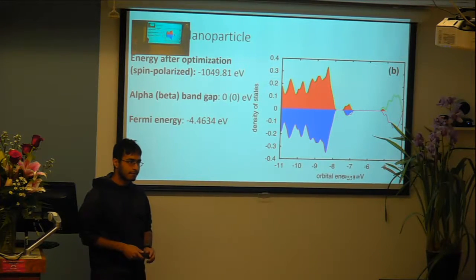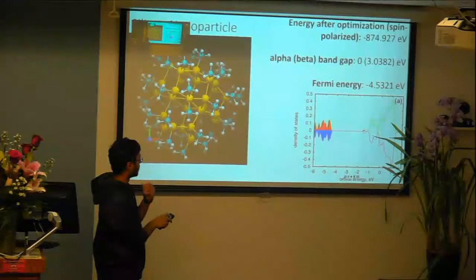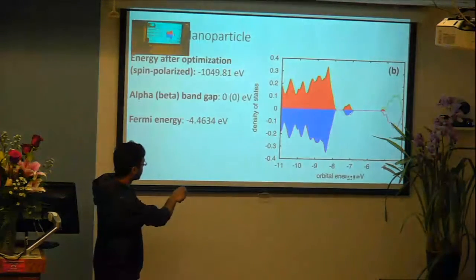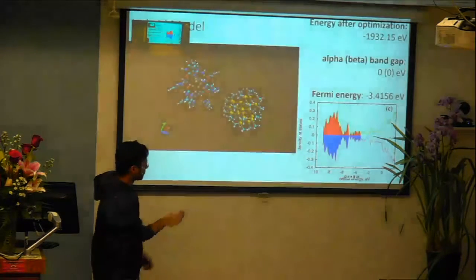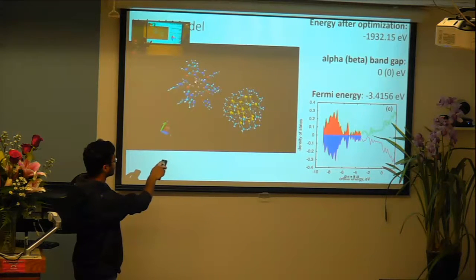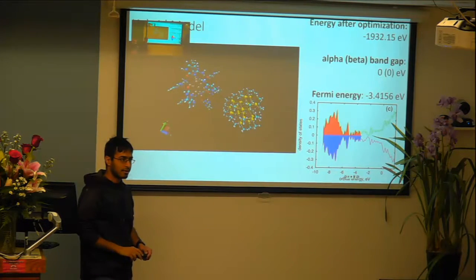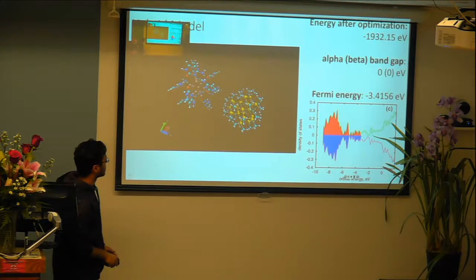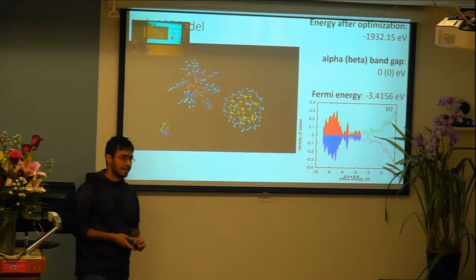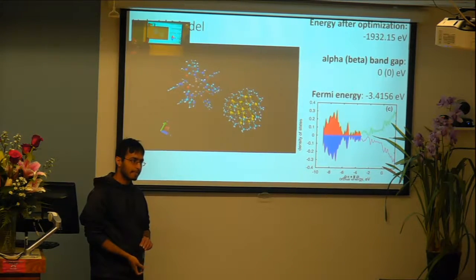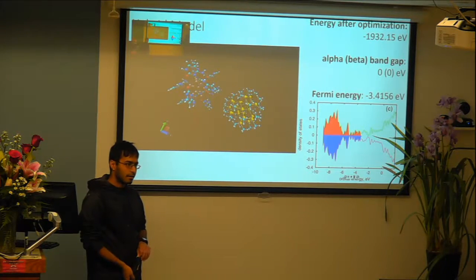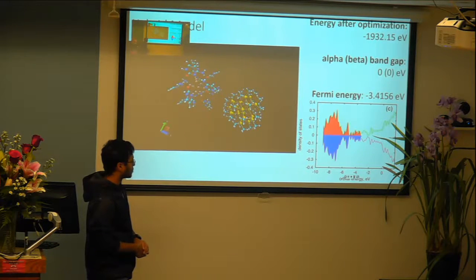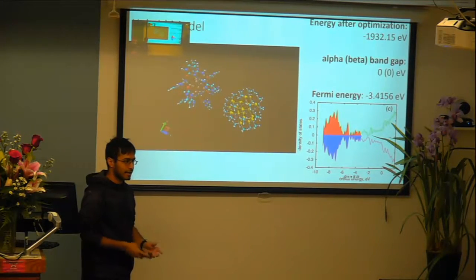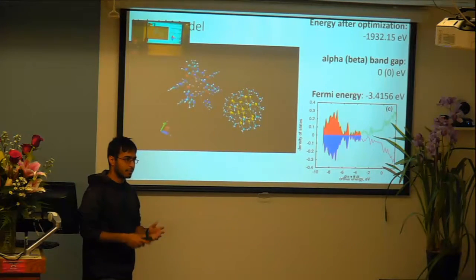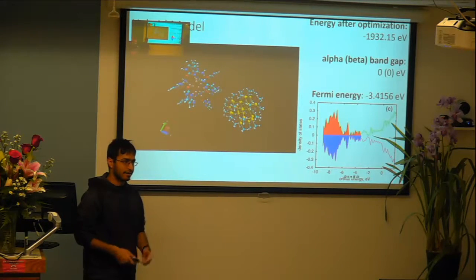And what is the distance between these two, the silver nanoparticle and the silicon part? It's very low, I believe. I mean in the two-model pair system. I forget the amount. Here we go. Are you talking about center to center distance, or surface to surface separation? Surface to surface. Okay. I believe that was approximately 5 angstroms, somewhere between 5 and 10 angstroms. So do you think that they're supposed to have any interaction at that distance? Any charge transfer possibility? Charge transfer, most likely not. But interactions like binding energy, that would be present. So binding energy would be a little bit positive or a little bit negative at that distance.